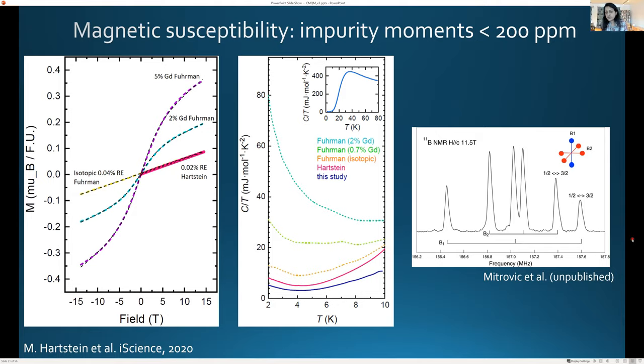The other way we have to probe locally whether there's any inclusions is that our collaborator Vesna Mitrovic has done NMR on these materials, and there's a whole separate result about the fact that 1 over T1T is finite. It looks like a metal, but I'm not going to cover that here, and Vesna will be able to talk more about that. But what I am going to point out here is that the line widths of the boron 11, which she studies, are extremely narrow. So this strongly argues against an inhomogeneous distribution within the material.